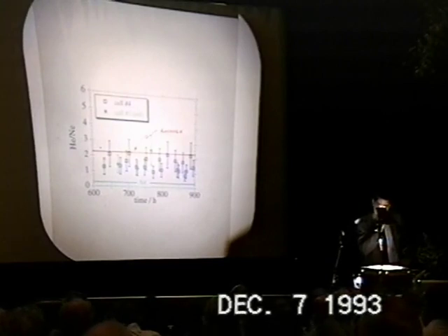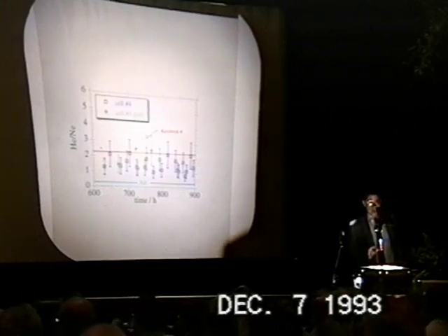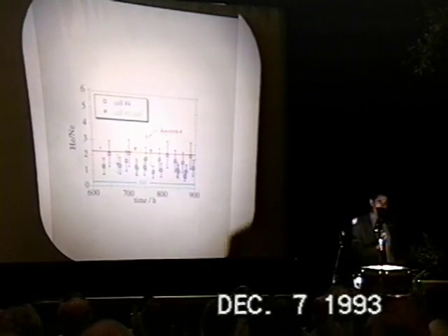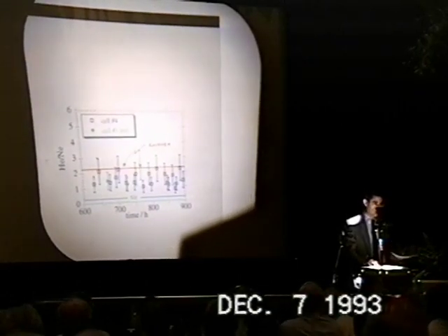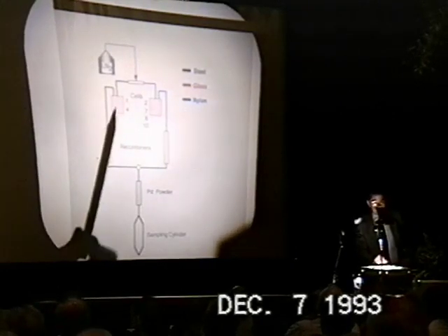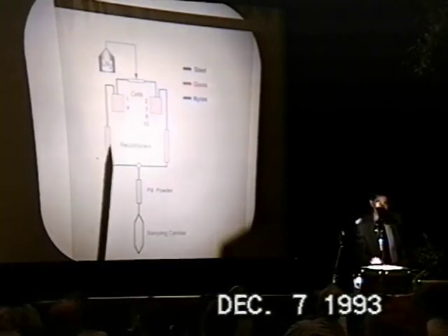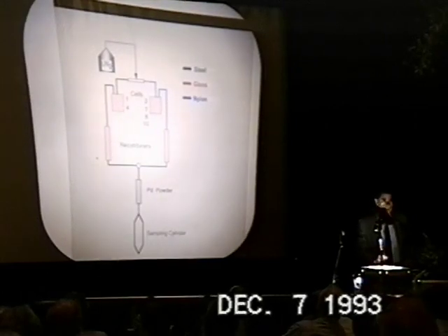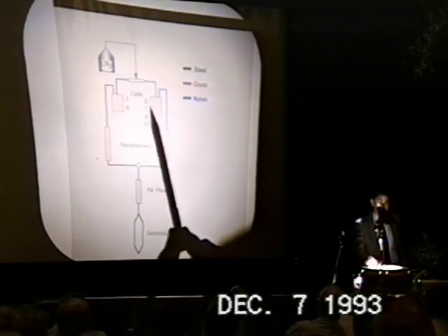However, it can also be that we have a combination of mechanisms, but I would like to state very clearly here that it can be, in my opinion, a consequence of the materials. It can be permeation, because the materials used for cell number 1 and 4 are exactly the same. Stainless steel is used for the cell and for the combiners, and the stainless steel joints are made with the same materials. This is also true for 2 and 7, 8 and 10.